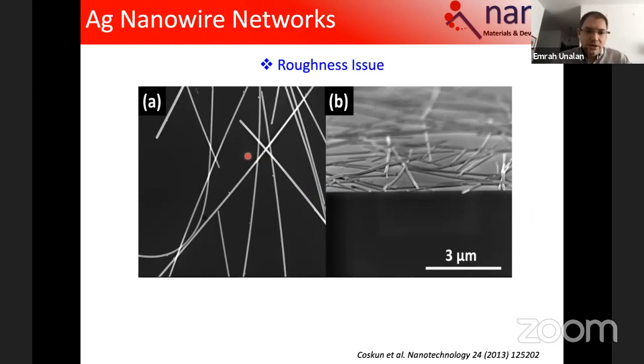But when you look into these films of nanowires, you would immediately realize that there is a roughness issue. Right, so this needs to be prevented first of all. If you put 100 nanometer thick polymer layers, the roughness is such that there are 3 to 4 to 5 nanowires on top of each other in some locations. So 100 nanometers of polymer will certainly short at these points, and the electric field distribution will not be uniform. So this roughness issue has to be prevented.